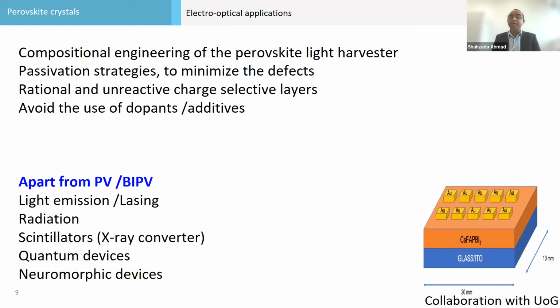Passivation strategy to minimize the defects, because perovskite is highly polar. And there is not a very good interface formation between perovskite and the hole selective contact. We need to develop a rational and unreactive charge selective layer, a P-type layer, which is dopant free, and avoid the use of dopants and additives.